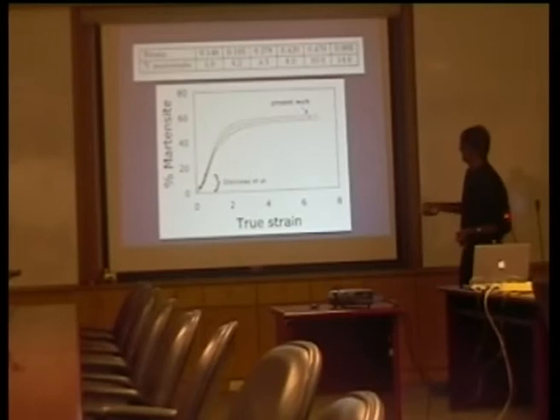But the experiments done at NTU show that the curve levels out like this. So we end up with only 57% of martensite after a huge strain. This set of results and this result are contradictory.